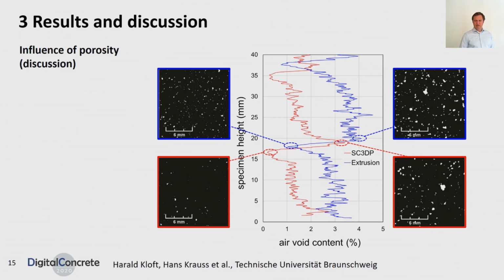So now, first we have to keep in mind this strong inhomogeneity, which is expected to have an influence on mechanical properties. And second, we have a difference between shotcrete 3D printed and extruded specimens. Evidently, also in case of extrusion, we have a good compaction beneath the interface zone, which may be exhibited by the extruder head compacting the substrate layer when it slides over it. And here we have an even better compaction in case of shotcrete 3D printing, which is due to the high kinetic energy of the material. And the sand grains may be penetrating into the substrate.